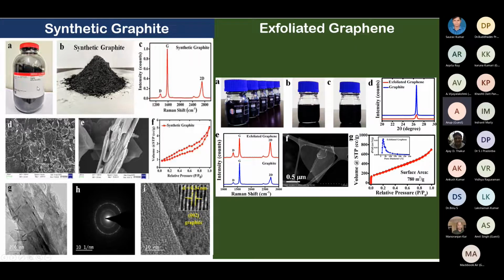We did multiple experiments to understand the initial phases and the morphology of the synthetic graphite from Sigma Aldrich, which you can see on the left-hand side, by X-ray diffraction, then SEM, then TEM, then BET surface area. We understood the initial surface area of the graphite. Once we had all the required data of the initial synthetic graphite powder, we started feeding this powder into the plasma spray.